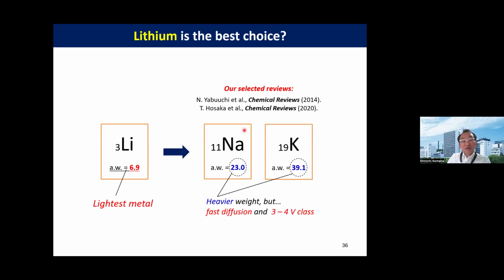So we already published two very extensive review papers in Chemical Reviews for sodium and also potassium ion. As I already mentioned, the atomic weight is heavier than lithium. However, the diffusion rate, the mobility of potassium and sodium ion, should be faster than lithium. And also the working potential, the working voltage of the battery, should be comparable to lithium.